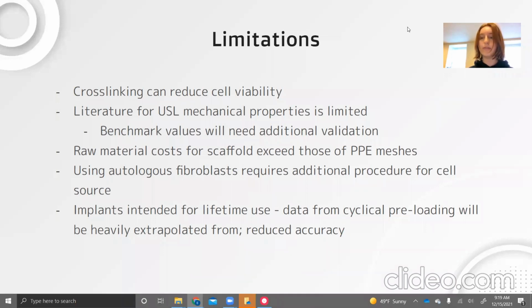However, like all medical implants and techniques, this approach is not without its limitations. First of all, the cross-linking involved in getting the collagen to last longer can reduce cell viability. So getting the balance between those two properties will be very important. The literature available for uterosacral ligament mechanical properties and other properties as well is also limited. So any benchmark values that we have will need additional validation. Also, the raw material cost for a collagen scaffold exceeds the raw material costs for polypropylene meshes, which means the final cost of the finished product will likely be more expensive as well.